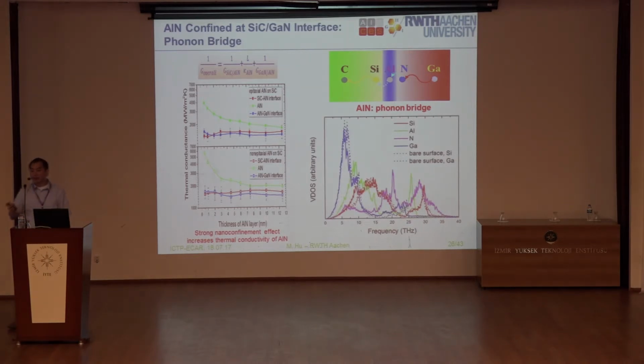So it's more like a similar idea as Professor Henry presented just half an hour ago. So we found that if you take a look at the vibrational density of states, the density of states of aluminum nitride happens to fall somewhere between the silicon carbide and the gallium nitride. So then actually the aluminum nitride can serve as a phonon bridge. So then the phonons, the energy comes to here, and then you can transfer to the aluminum nitride and then transfer to the silicon carbide. Of course, this depends on the vibrational density of states. If the vibrational density moves into some other regions, then of course this does not help at all, right? So you have to carefully choose the third material.